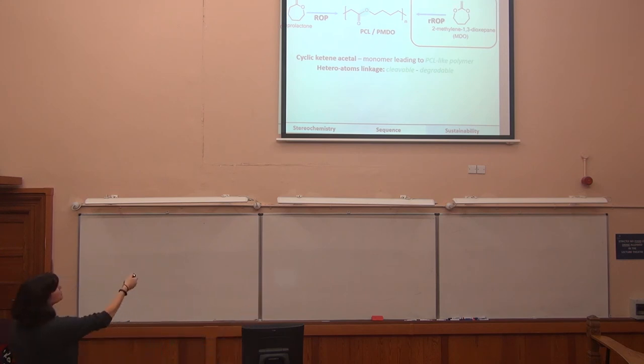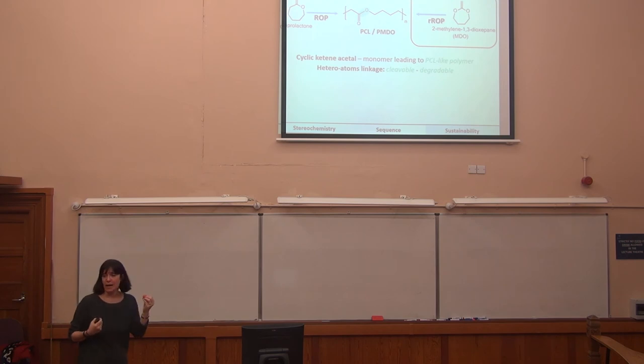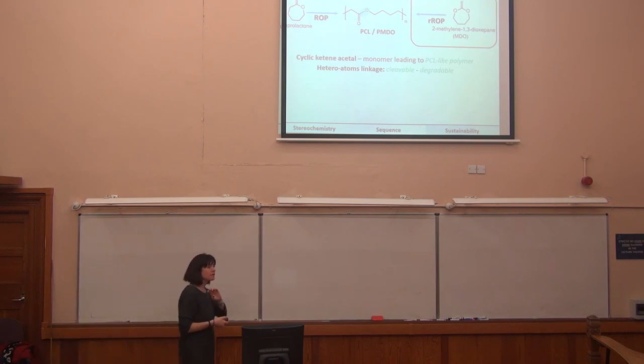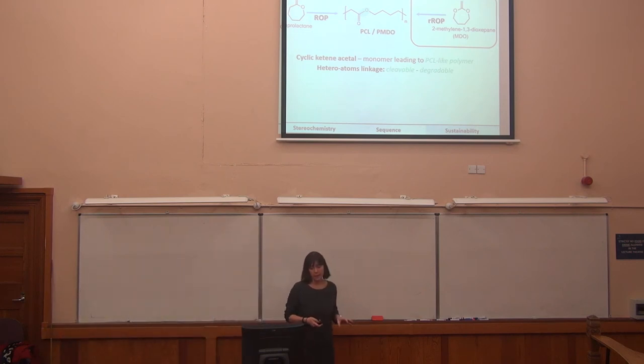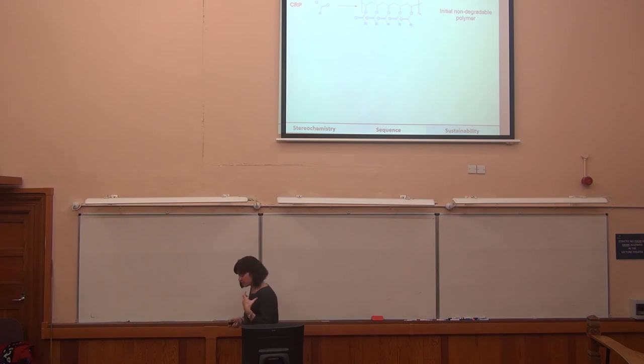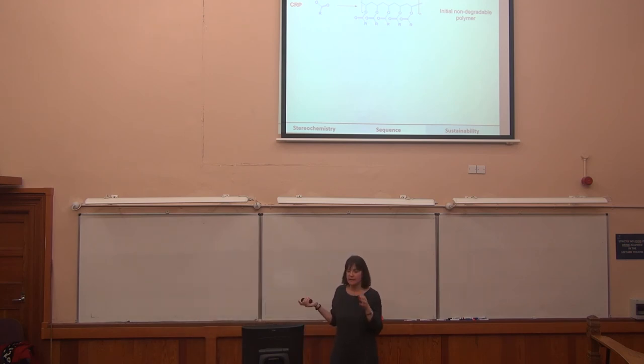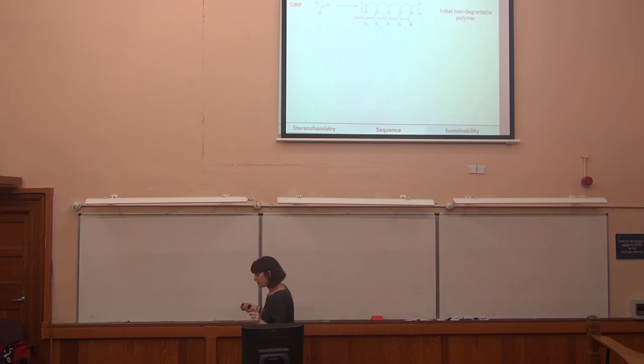When you polymerize it, you actually form a polycaprolactone-like material. We're quite interested in introducing these heteroatoms into the backbone of conventional carbon backbone polymers. So we do a lot of CRP, controlled radical polymerizations. Super easy, you can do them in bulk. Our undergrads do them in the lab, really, really easy. You can make kilograms of materials very easily in the lab, but you form this carbon backbone polymer that's not